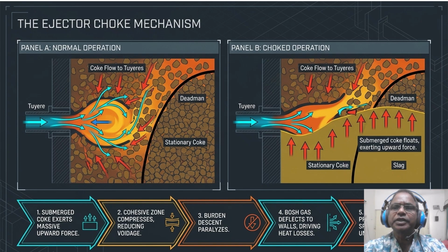In normal operation, gas and coke flow freely toward the tuyere, but look at panel B. As slag level rises, this submerged coke exerts a massive upward buoyancy force. So this buoyancy compresses the cohesive zone, reducing coke voidage and essentially paralyzing burden descent. So this is the ejector choke.